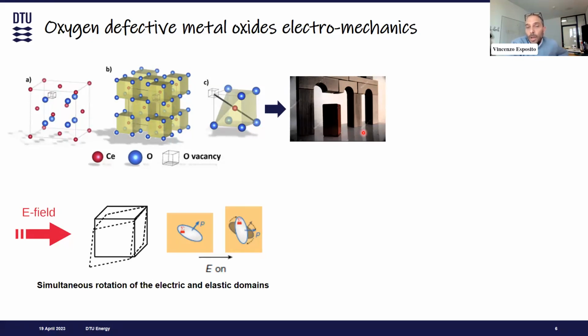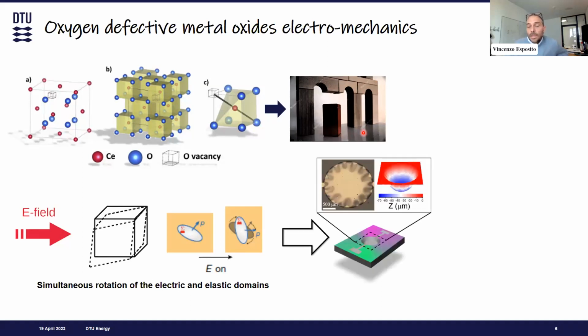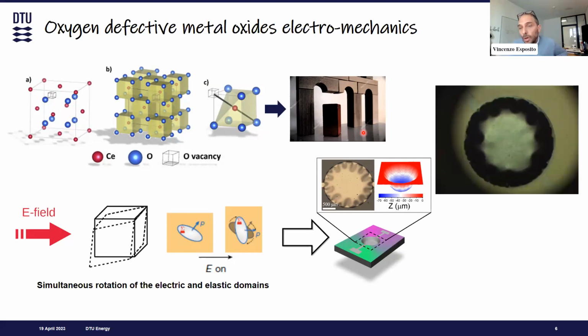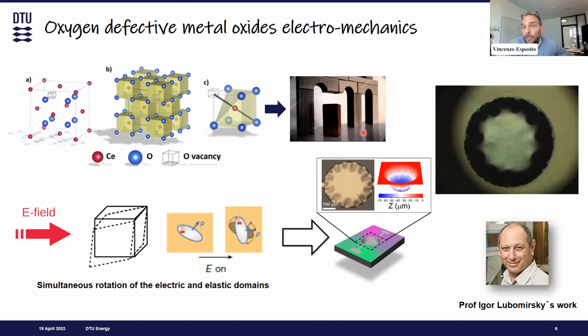and trigger an electromechanical response. This has been shown not by us, but some time ago already, in 2012, by Professor Lubomirsky from the Weizmann Institute of Science. And he demonstrated this principle in cerium oxide, which is one of the defective materials with a fluorite symmetry, where in a thin film shape under a pretty low electrical signal, you can actually have some actuation, very important actuation, actually pretty large.